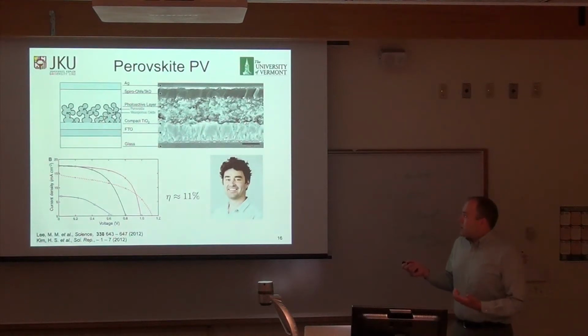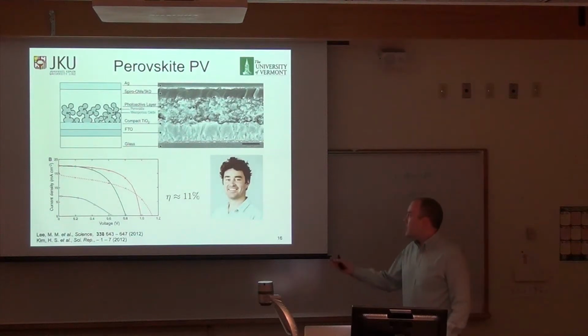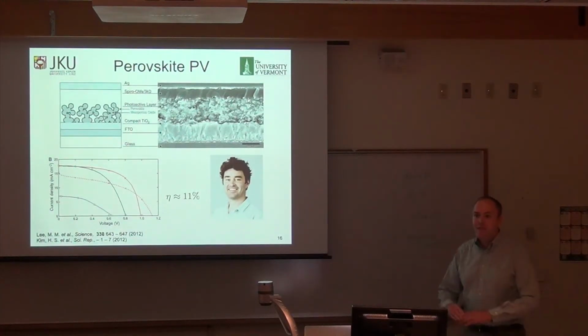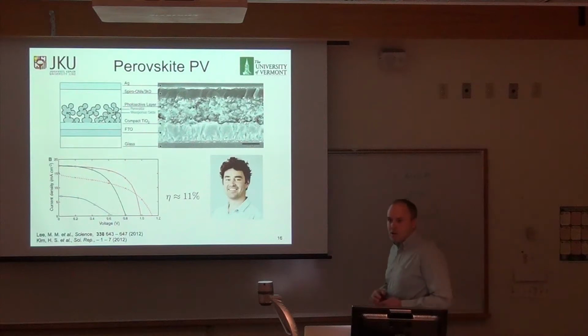The reason for having the mesoporous structure, they claimed in the original paper, was that it increased the surface area for this functionalizing dye, which is the perovskite. That is completely not true. It's become very clear — even the year after, Henry Snaith himself published a paper saying, forget it, I was wrong, we don't need that. But that was the original idea. It turns out that the mesoporous structure just makes making the top film easier. So this problem of making a continuous film is alleviated by having the mesoporous structure. If you could alleviate it some other way, your device or manufacturing process would be a lot better.